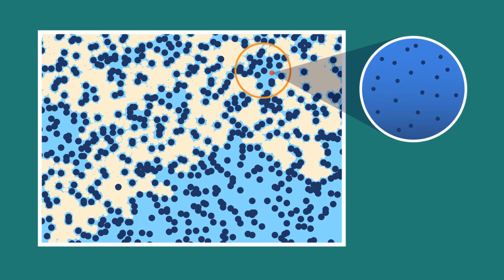A similar but larger scale situation would be found in porous materials containing patches of solution that are isolated through small pore entries. In such cases, drying can cause the local salt concentrations to increase substantially, implying that stones with such inhomogeneous pore size distributions are at a higher risk of salt damage.